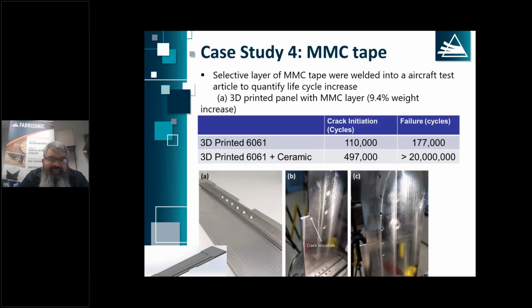Another case study is looking at some of the metal matrix composites. And the idea here is really just to show you how a little change in mass can have a huge effect on performance. This was another program for NASA Langley on a similar geometry that we looked at in the embedded sensors. We printed one completely monolithic out of 6061. So the whole thing was printed 6061. And then we printed another one with 6061 and about 10% by weight metal matrix composite, so Nextel fibers in this case. And then we put both of these through a testing regime.